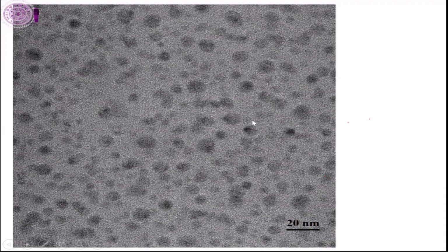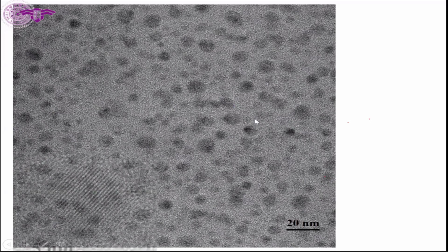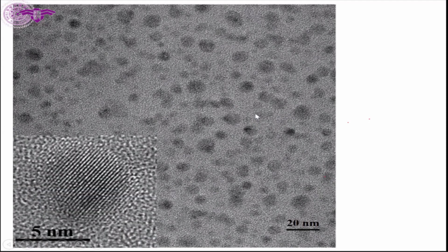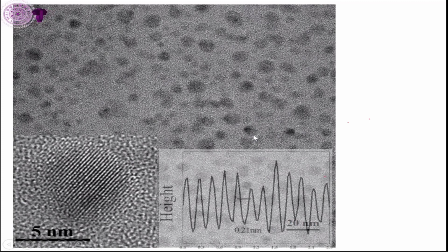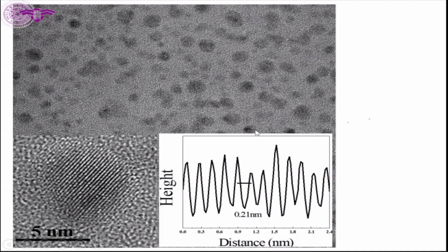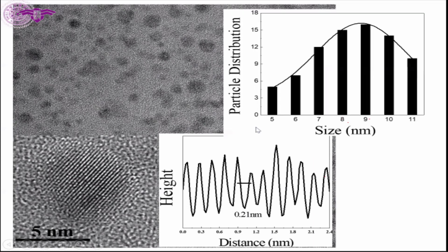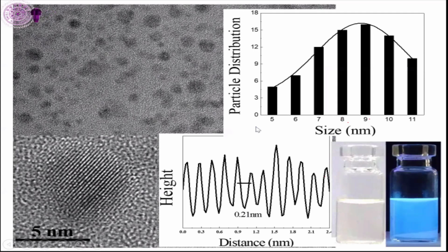I just very briefly and very quickly want to show that we still can see a lot of the graphene quantum dots. This spacing is 0.21, very close to carbon. Their particle size is around 9, very similar to the GQD we fabricated from passion fruits, and you can see that they have quite a good optical property.